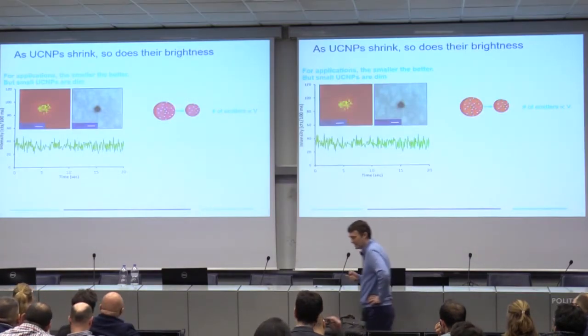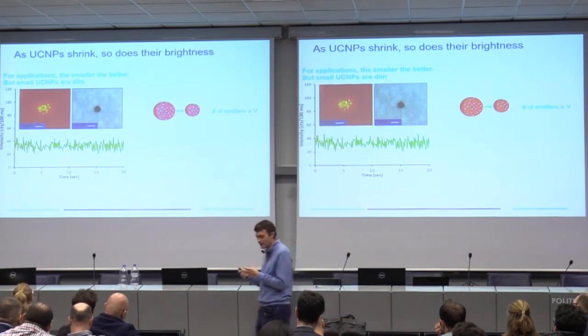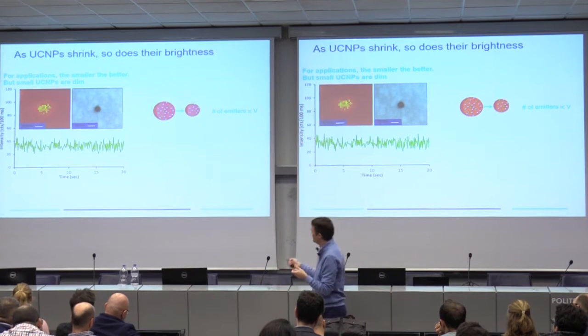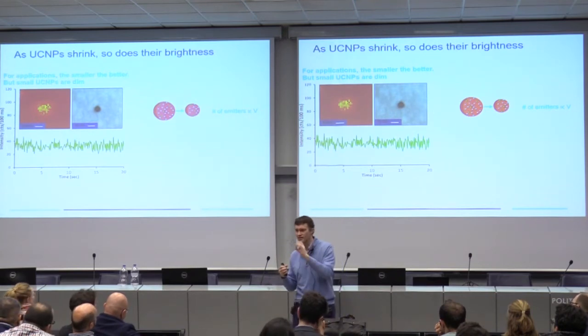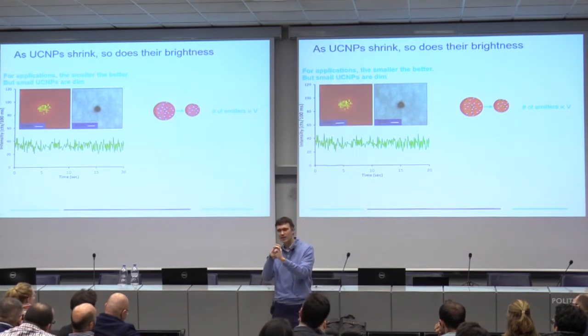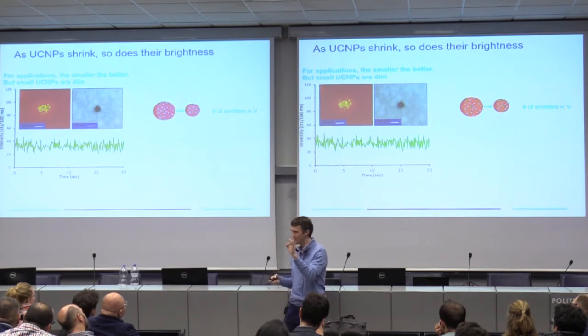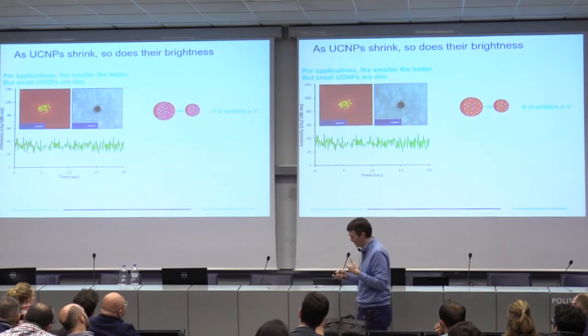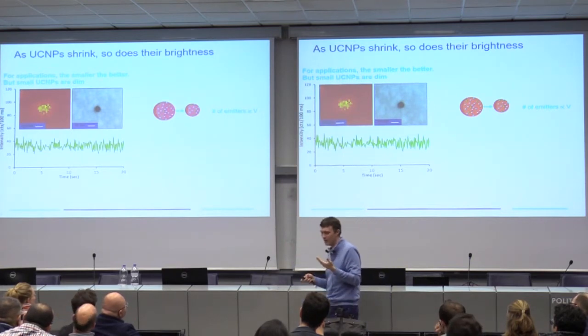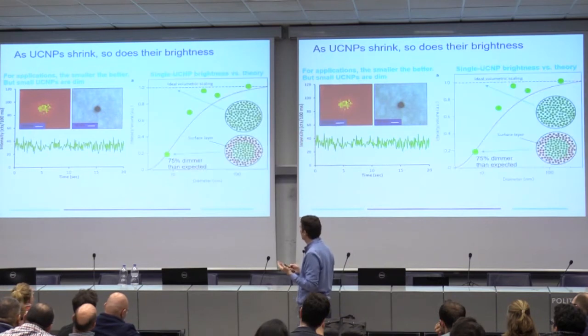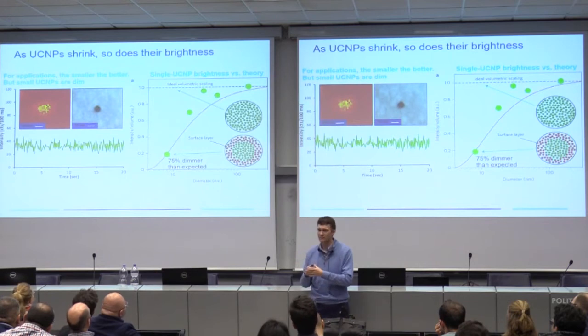Okay, so the way that these particles work is you've got a nanoparticle. Say you start with a big one, say 30 nanometers, and all it is is a nanoparticle with emitters stuffed inside of it. As you make the particle smaller, it gets dimmer, because you literally have fewer emitters inside the particle. It's one thing if that's the only problem, right? You have this volume scaling, but it actually is worse than that. It turns out that even if you correct for this volumetric scaling, as they get smaller, they get really dim.